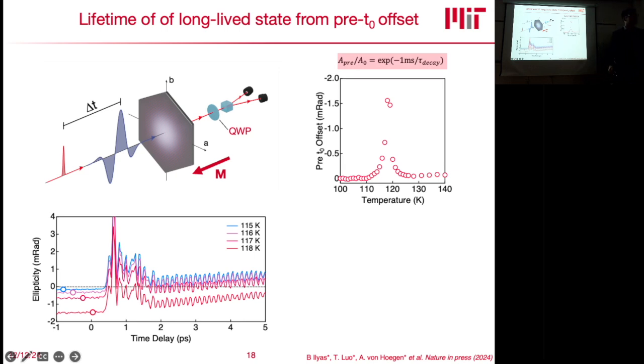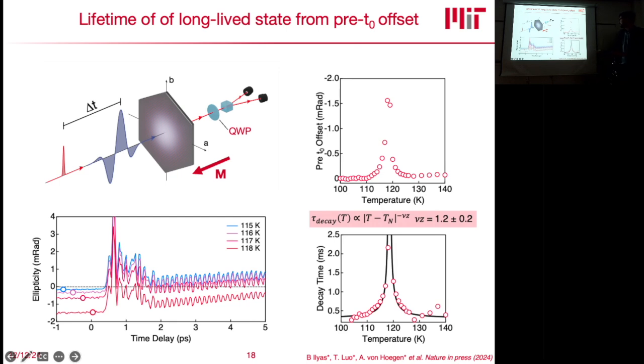So what we did is purposely change the repetition rate of our laser. Instead of pumping every 2 milliseconds, we now pump every 5 milliseconds. We changed the chopping scheme and observed a very similar effect, which led us to a very similar expression for the decay time. Yeah, but those are details that I try not to burden people with. Thanks for pointing that out.